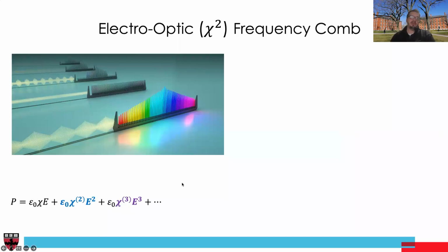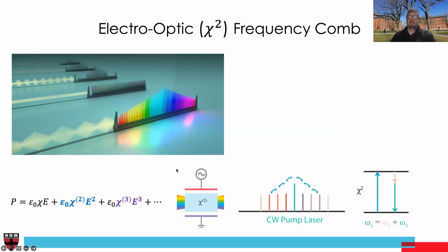And in contrast to the Kerr frequency combs that I discussed so far, that rely on third order nonlinearity, electro-optic frequency combs rely on the second order nonlinearity of lithium niobate. And basically, the simplest way to think about this is actually not an amplitude modulator, as I mentioned in the previous slide, but a phase modulator. So you take lithium niobate, apply an electrical RF signal, generate sidebands, and then you drive this phase modulator harder, generate more sidebands, and that's your comb.